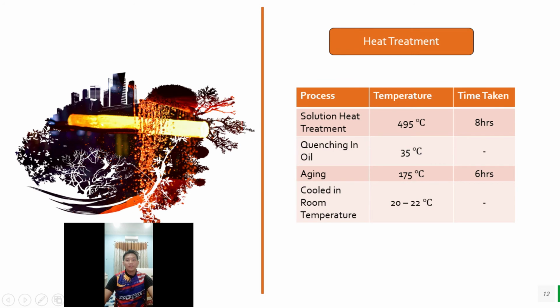This is the heat treatment parameter for the hardening process in this project. The process includes solution heat treatment, quenching, aging, and cooling. For the solution heat treatment, the temperature is 495 degrees Celsius for 8 hours. Quenching in oil at 35 degrees Celsius. Aging is 175 degrees Celsius for 6 hours. And cool at room temperature, about 20 to 22 degrees Celsius.